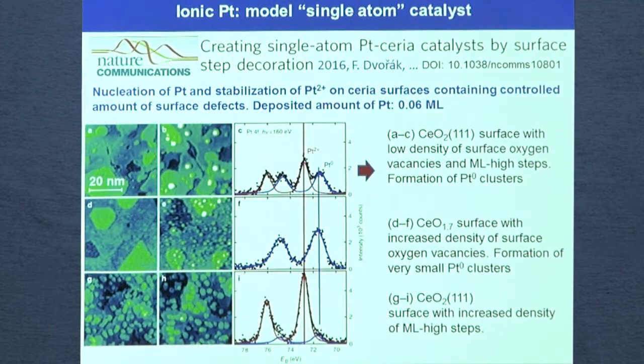And now we can use this kind of model for investigation of platinum interaction with cerium oxide. Here you can see a very new paper published this year, where we prepared different types of surfaces. So this one is CeO2(111) with a very low density of surface oxygen vacancies, and we deposited, in this case, 0.06 monolayer of platinum. And you can see that the platinum is in two states, platinum 2+ and platinum 0.